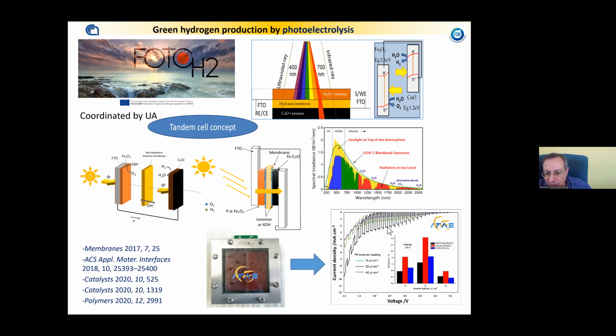And this on-off polarization curve is a photodiode representation model. You can see something like 5 milliampere per square centimeter at practical cell voltages.